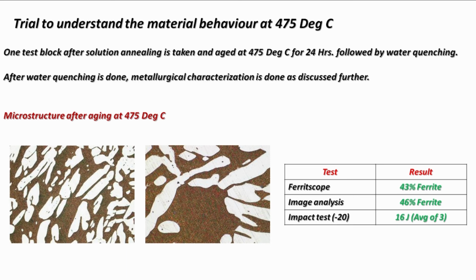However, if we see the impact toughness of the material in solution annealed condition, the impact toughness is around 164 joules. But after exposing to 475 degrees Celsius, we can see a great fall in the impact toughness to 16 joules, which is nearly 10 times lower, indicating the material has become brittle.